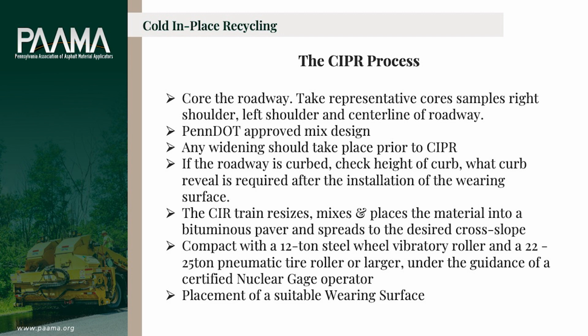And then we do whatever the cross slope is. We can change the cross slope sometimes within inches, not feet. We can't change it drastically, but we can change within a few inches the cross slope itself, taking it to a 2 or a 3% cross slope. Compaction-wise, 12-ton vibratory steel wheel rollers, 22 to 25-ton pneumatic tire roller. It's not a chip seal roller. It's a roller built especially for cold in place. It's 25 ton.